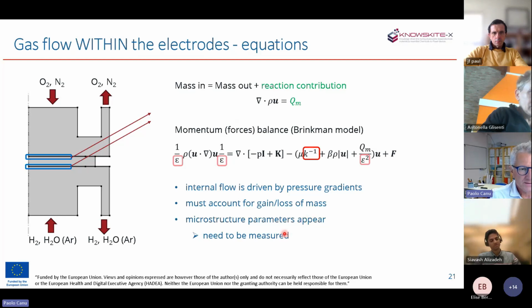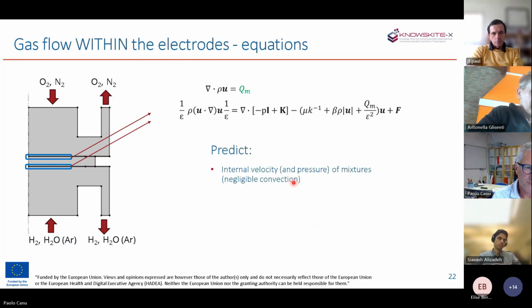So we already see that the parameters mentioned, porosity and permeability, appear in the equation, and they basically determine how easy the transport of species across the porous electrodes would be. Once this additional equation is solved within the domain of the electrode, it allows us to predict the internal velocity, although it's not so relevant because if the electrolyte is gas tight, so there's no possibility of total gas flow beyond the electrode, the velocity inside the porosity is fairly small. So the whole set of these equations is not so important.